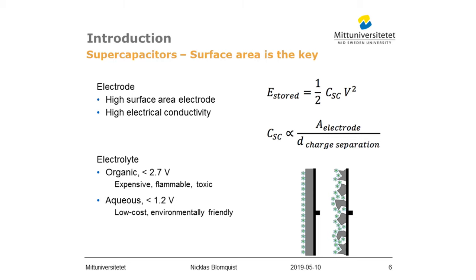Another part of the supercapacitor is the electrolyte. There are several kinds of electrolytes, but the 2 most common are organic and aqueous. Organic electrolytes have a high operating voltage at about 2.7 volts. And this, of course, gives a massive boost to the energy storage since the energy storage is proportional to the voltage squared. But on the downside, they are expensive, flammable, and in some cases also toxic.